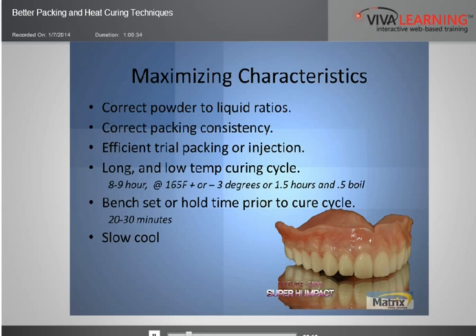I also do something that you won't find recommended in most instructions, and that is that I bench set or hold my packed case under pressure on the bench or in the cold water in my unit for about 20 to 30 minutes. It does a couple of things. It allows the monomer to imbibe into the polymer. It allows the solvent, which is the monomer, to affect the tooth interface so that you get a better bond. I also, another way to maximize your characteristics is always go with the slow cool.